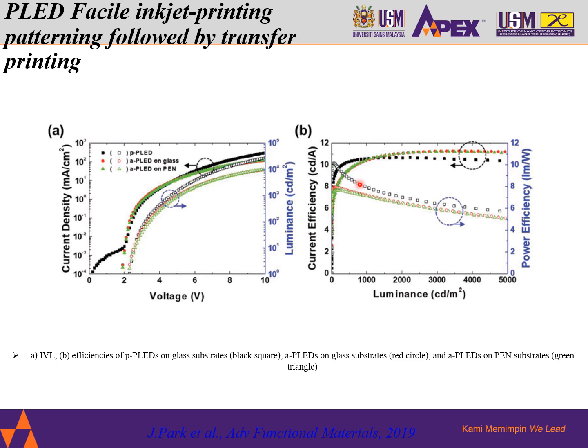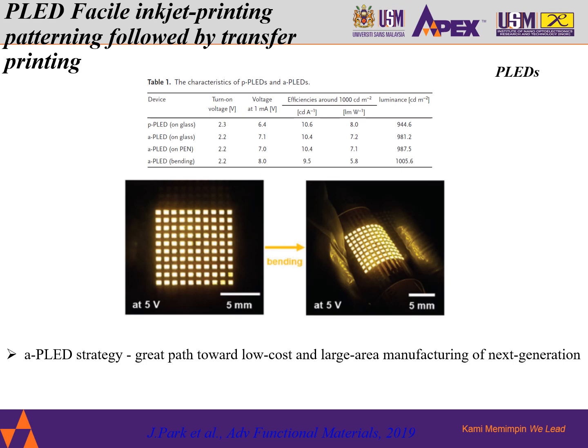Although there is a slight difference between their profiles, which they believe came from the device structures and physics, such as the energy barrier, charge injection and interface property, and top and bottom emission characteristics. The device characteristics of all devices are summarized here in table 1. This group achieved excellent transfer printing yield with the blended PEDOT:PSS ink formulation, which was optimized, and adhesion properties of each film with various substrates at each step were very well controlled.